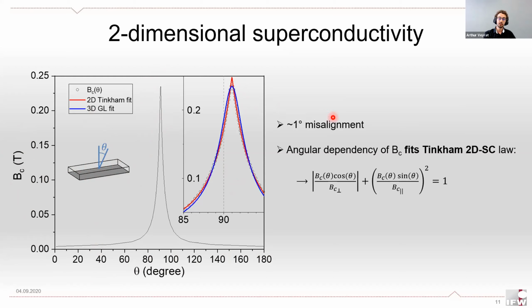This 1 degree offset is actually simply due to a misalignment of the sample inside our measurement apparatus, since the sample is simply plugged in by hand in the measurement device. So if we take that misalignment into account, we can fit our data using either the two-dimensional Tinkham model or the three-dimensional Ginzburg-Landau theory, respectively in red and blue. And as you can see, the two-dimensional model in red fits our data much closer. So this is a good indication that we have two-dimensional superconductivity in our sample.